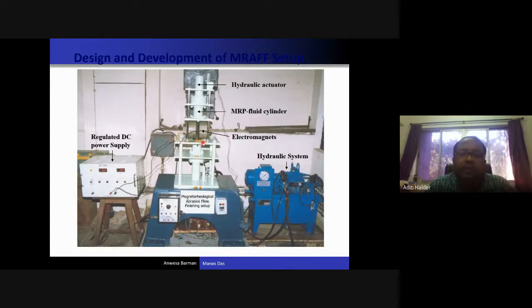So this insulating layer over the copper wire is the main problem. Because of that it has a rating. So it may be 100 degrees centigrade, 120 degrees centigrade, like that it can work. Okay, so we are using this DC power supply, around 5 ampere current we are giving. So almost 0.5 to 0.6 Tesla we can get from this electromagnet. But these coils are very heavy, and also this core material is the more important thing here.